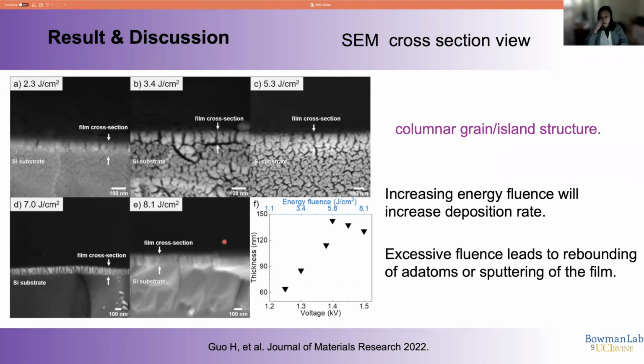It's because excessive fluence leads to rebounding of the atoms or scattering of the atoms. Very high kinetic energy of the adatoms. So these atoms with high kinetic energy will rebound from the surface of the substrate. So the whole thickness of the film drops. Also in the cross-section SEM image, you can see a very clear 3D island structure of the columnar grains and islands. Also, you can tell some nanopores vividly.